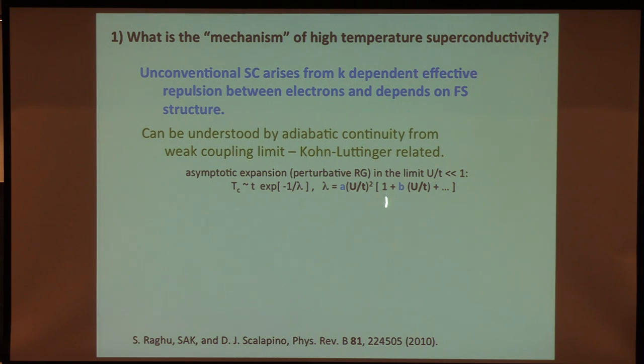On the other hand, if I extrapolate this to interaction strength of order 1, then at least I have no other small parameters here. The prefactor here, since this is a purely electronic mechanism, and since this comes directly from the repulsion, one can hope that the prefactor is some characteristic electronic energy, not some phonon energy. So we get 1 or 2 orders of magnitude in TC just by the prefactor, even if we extrapolate all answers to lambda equals 1. Now, that's extrapolation. You might say that you think I'm not allowed to use this unless lambda is less than 10 to the minus 2. And of course, I can't argue with you, and e to the minus 100 is really bad news.